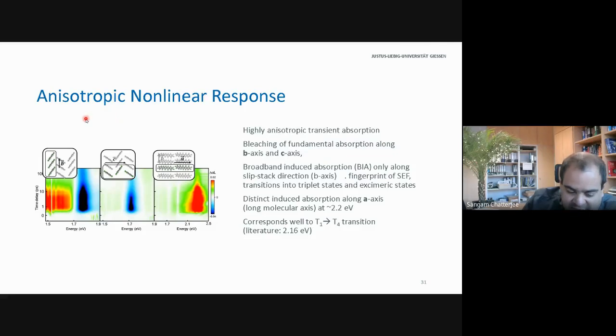Here, while the linear absorption spectra look different, the nonlinear absorption spectra look terribly different. You see induced absorption along the B axis for low energies, which you don't see in the other spectra. You see bleaching at the exciton resonance, but it's different for the B and C direction. And along the A direction, something totally different is happening. You see a very, very strong induced absorption resonance.